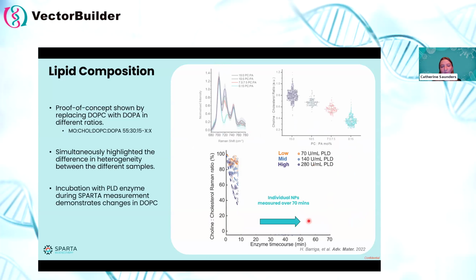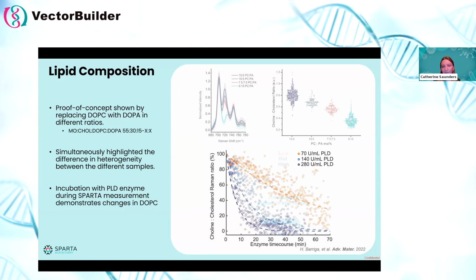And then, of course, what's really interesting to do here is to look at this in terms of kinetics, so looking at a time course analysis. Having related the signal to the change in the choline to cholesterol ratio, we can then track this over time. So what the researchers did is that they took these nanoparticles, incubated them with different amounts of the enzyme, so low, medium, high amount, and then they measured this for just over an hour.